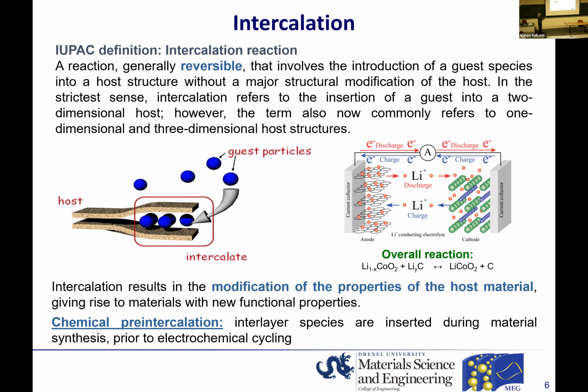But this is done electrochemically in the battery. So what we do is intercalate ions in the course of the material synthesis. That's why we call this process chemical pre-intercalation, which implies that we do insert different ions into the interlayer region of our materials, and we can change the interlayer distance, but at the same time, we do it prior to electrochemical cycling. Then we use these chemically pre-intercalated materials in order to study the energy storage properties in the electrochemical intercalation reaction.